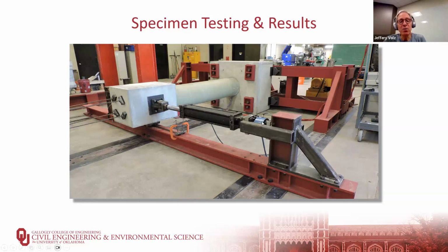And then here we have our load cell protected to make sure everything stays in alignment. These are the wires that come out for the strain gauges that are on the steel tube. We also have strain gauges installed to measure the hoop stress in the FRP tubes. You can barely see them. These are the little silver dots right here. And we have those to measure the hoop strain that the FRP tube is experiencing.